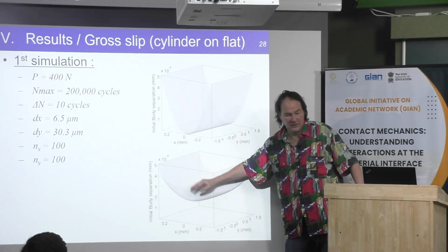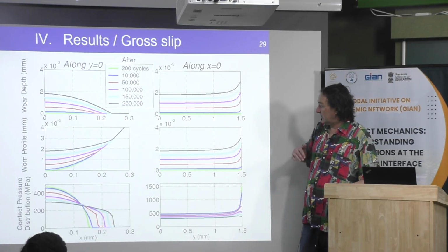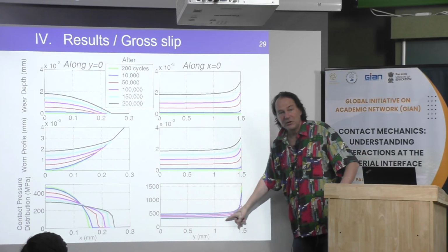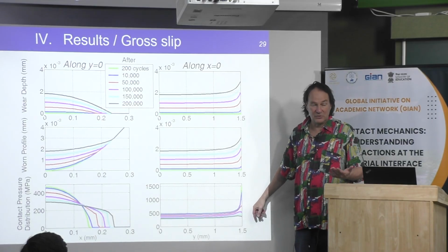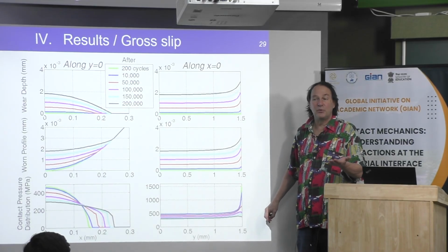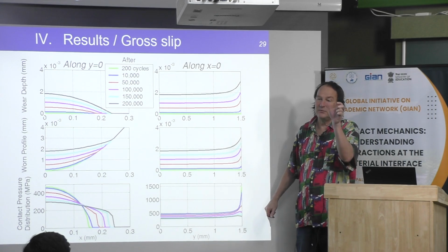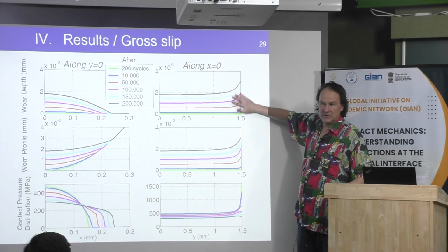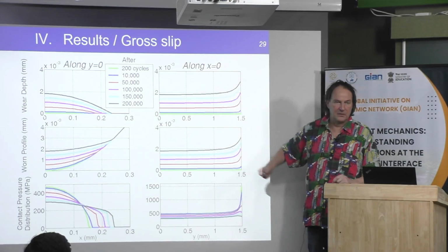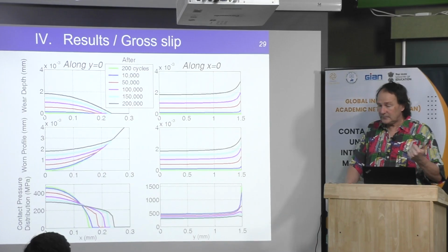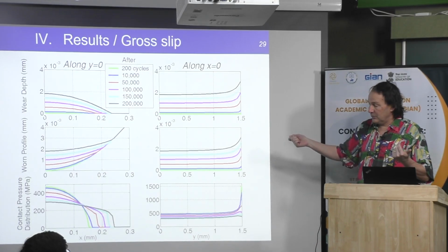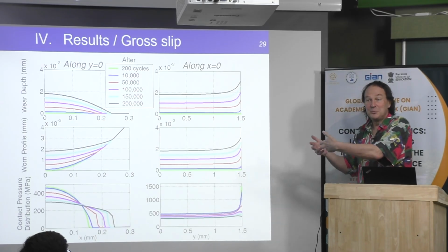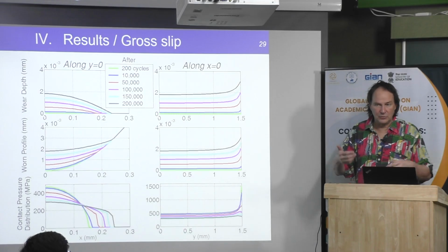Okay. And if you go like that at the infinity, you may have also a perfectly flat pressure distribution, in fact the optimum pressure distribution, and you will find again the logarithmic profile. Just if you change the load, of course, it will change the profile. And here this is the wear geometry. Okay, is it clear? As I said this morning, if you have a complex geometry, the wear solution will be the optimum geometry, in fact, and you can use that to optimize something.